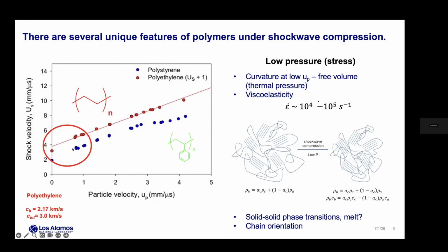So first I'm going to talk about the low pressure response of the polymers. What you can see here is that polyethylene in red looks pretty linear in this plane, whereas polystyrene has that cusp associated with it. And, in fact, we do not extrapolate to the bulk sound speed. The first thing I want to point out is that at low pressures, that's the region where you would expect different compressibility of the different domains in the polymer, as well as viscoelastic effects to be dominant. So you end up having curvature at low particle velocities in this plane. That's associated with compression of the free volume in the network. And then you're going to have viscoelasticity because commonly you're in the 10 to the 4th to 10 to the 5th strain rates in this regime.